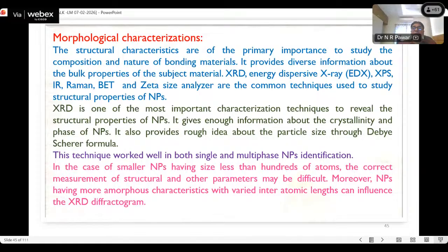It gives enough information about the crystallinity and phase of the nanoparticle. It also provides a rough idea about the particle size through the Debye-Scherrer formula. This technique works well for both single and multiple nanoparticle identifications. In the case of smaller nanoparticles having a size less than 100 atoms, the correct measurement of structural and other parameters may be difficult. Moreover, nanoparticles having more amorphous characteristics with varied interatomic length can influence the XRD diffraction.